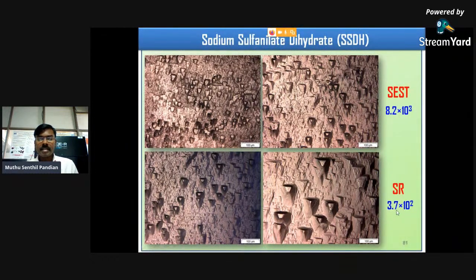So low etch pit density in SR method clearly indicates the crystalline perfection of the SR method grown crystal is very high, which we have already seen in the HRXRD measurements also. With low full width at half maximum with a single peak in SR method grown crystal, almost all the crystals show similar cases. So this is for 5 seconds, this is for 10 seconds. On successive etching for 5 to 10 seconds, the same etch pits enlarge their size, retaining their geometrical shape and do not disappear, thus suggesting that the pits are due to the dislocations. They are randomly distributed, but strictly oriented etch pits are seen in the conventional and SR method also.